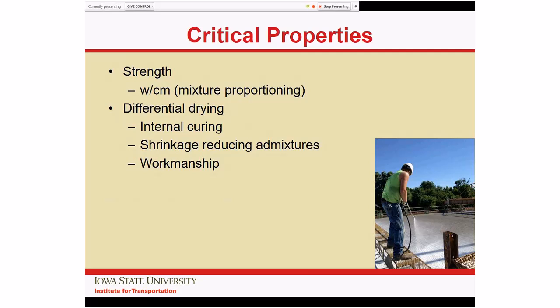On the other hand, we're also interested in that shrinkage and cracking issue. In particular, differential drying is that if a system is wet and cool at the bottom and hot and dry at the top, you'll end up with a differential across the thickness of the section, and so invite some fairly nasty cracking to occur. Ways that we can address this is, again, the internal curing, and I'll show you how this works a little bit later. Shrinkage-reducing admixtures just reduce the shrinkage overall, and also workmanship, in which I include conventional curing, finishing, those sort of activities.